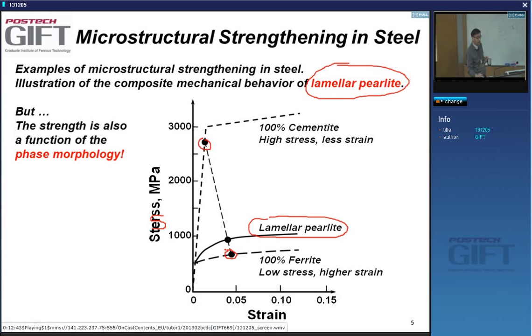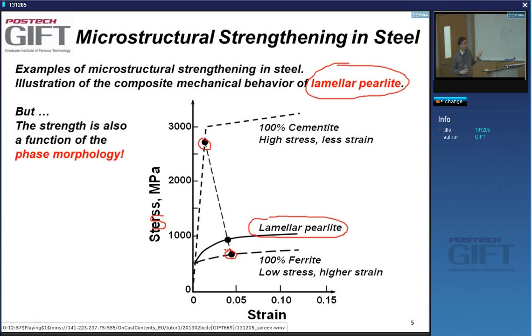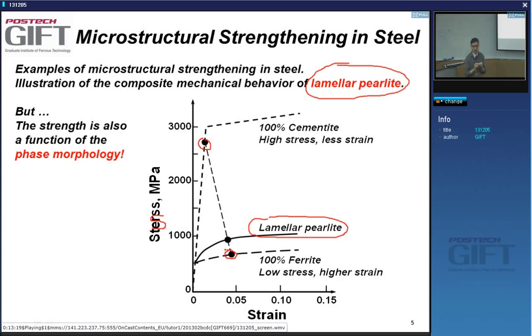This brings to the idea that if one phase doesn't deform at all and the other can deform, as soon as you apply deformation, the very strong phase will probably fracture. And that's what you see if you have small cementite particles in the microstructure and do a tensile test — these particles break or delaminate and are the cause of much trouble in terms of plasticity. However, if you do the same thing with lamellar pearlite, no problems. The cementite in lamellar pearlite can deform plastically.